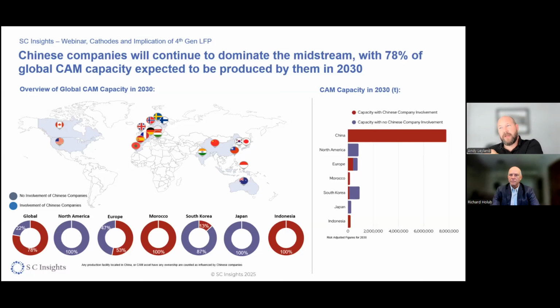Other entrants which are quite interesting is obviously Morocco. We've seen a huge amount of investment happening in Morocco. It's really one of the success stories at the moment. And interestingly enough, they have a free trade agreement with the USA, and they also managed to get a lot of financing from Europe. So Morocco is actually playing the linchpin between Europe and North America very well when it comes to supply chains. But as you see on the cathode side, that's very much Chinese controlled.